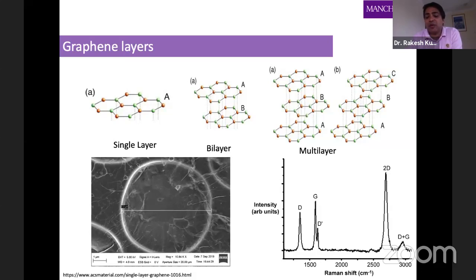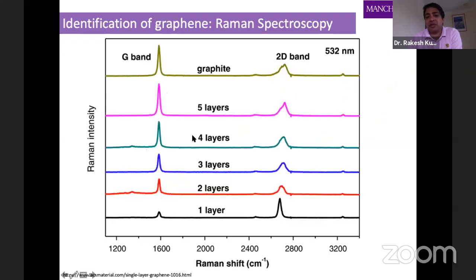But the most powerful tool to identify single layer or multilayer graphene is Raman spectroscopy. With Raman spectroscopy, you get signature peaks. From these signature peaks, like the D band, G band, and 2D band, you can easily identify whether your graphene is high quality and a single layer, and whether it is doped or not doped, a pristine graphene. As I mentioned, Raman spectroscopy can quickly and non-invasively provide you information about the quality of graphene and the number of layers of graphene.